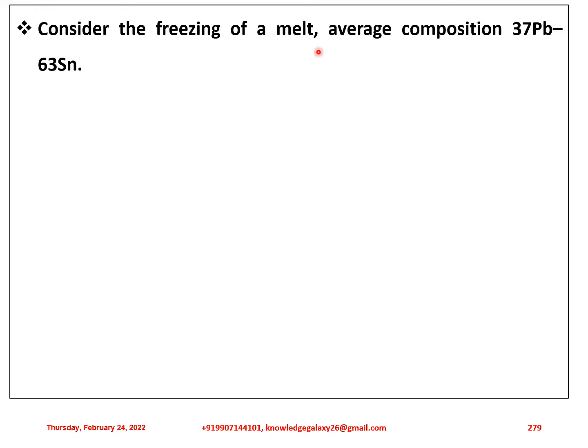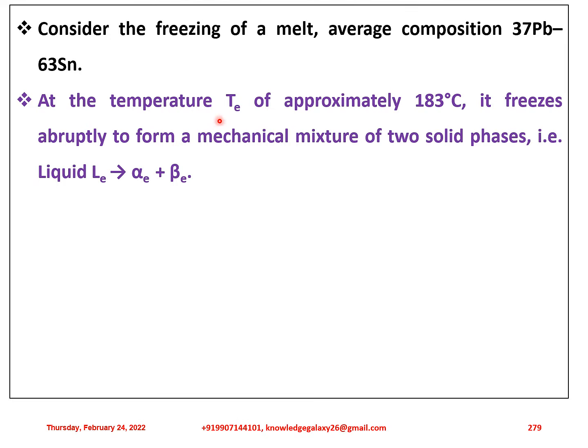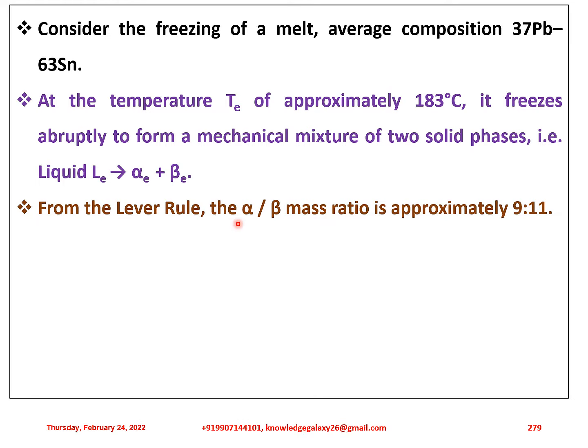Consider the freezing of a melt of average composition 37% Pb and 63% Sn. At the temperature T eutectic of approximately 183 degrees Celsius, it freezes abruptly to form a mechanical mixture of two solid phases; that is, liquid L eutectic transforms on solidifying into alpha eutectic plus beta eutectic. From the lever rule, the alpha to beta mass ratio is approximately 9 to 11.